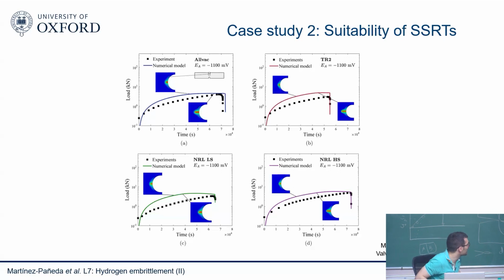And what the model is telling us here is that you have initiation of crack growth. And if you have initiation of crack growth, then this test is not valid. And the other problem that we found here is that you don't really know what to do with this test, because even to rank materials is not very useful, because basically people rank materials based on the failure load. But you could have a material where cracking initiates first, but because it has lower diffusivity, the crack propagates more slowly, and therefore the time to failure happens later. But cracking initiates first, so depending on your problem, that initiation of cracking could be a problem.